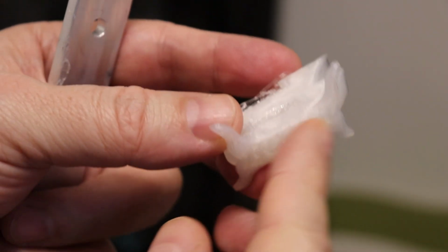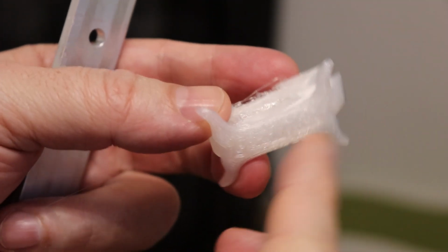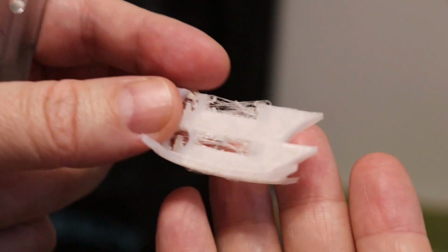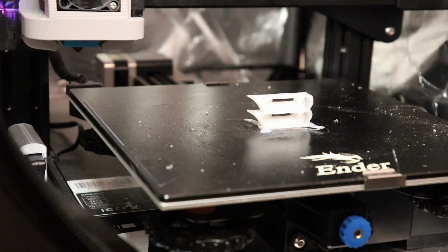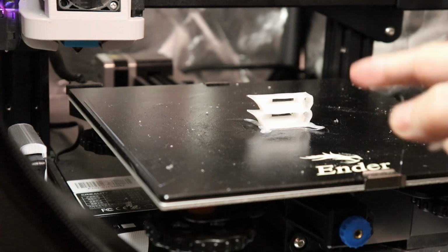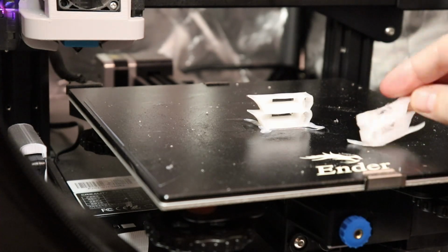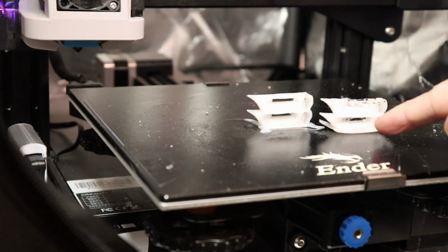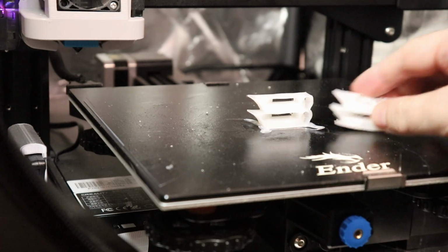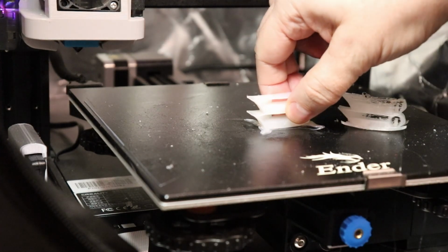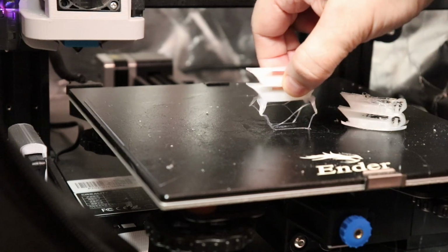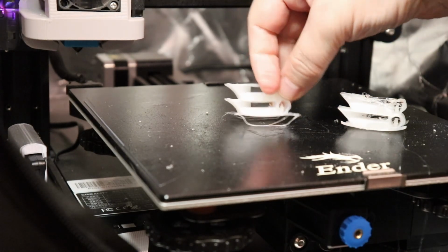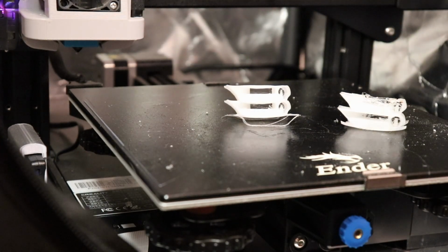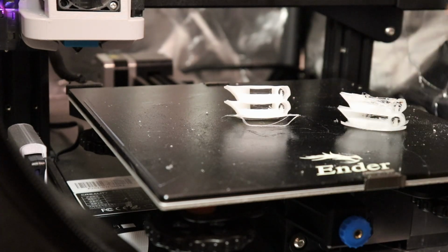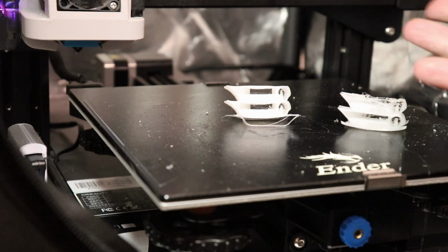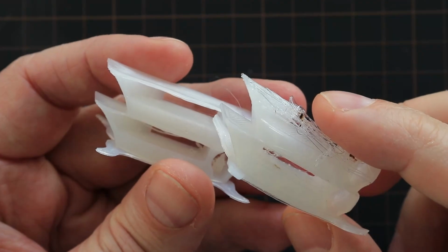And actually, I don't know, maybe add a little bit more glue stick. I don't have other ideas. So this is the temperature tower from 240 to 230, and this one which failed was between 260 and 250. So definitely a lower temperature helps against the warping, but it's far from perfect. But for better mechanical strength, I will print everything at 250 degrees Celsius, one by one, each specimen.